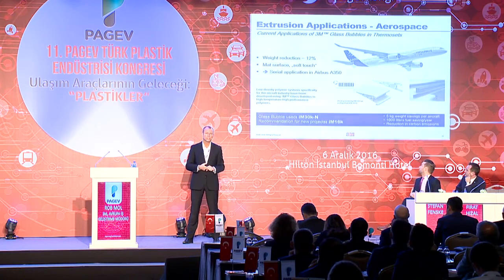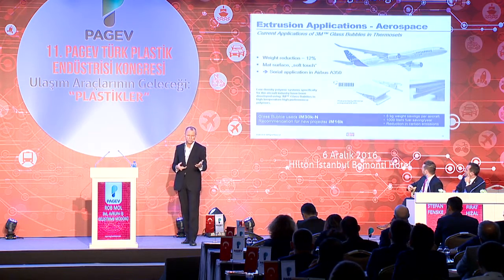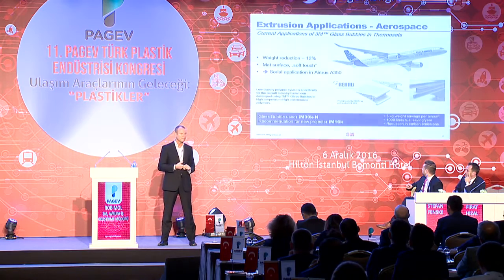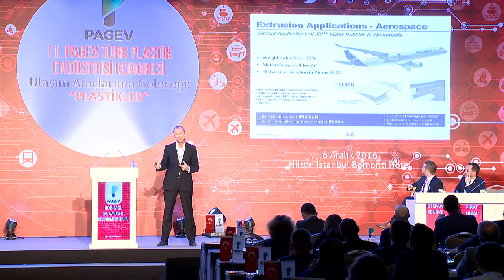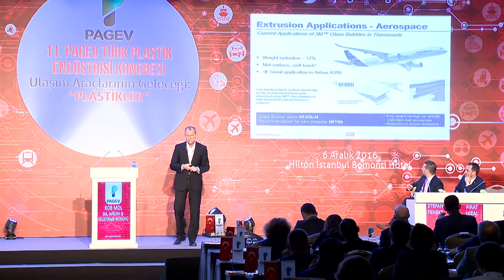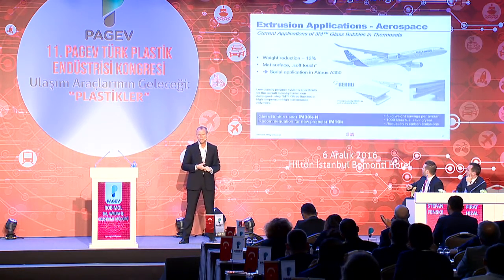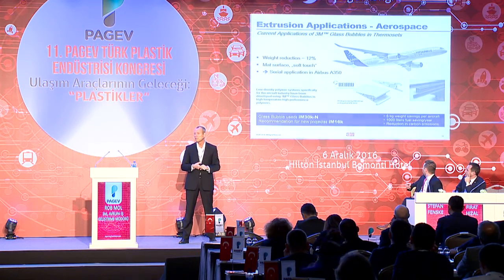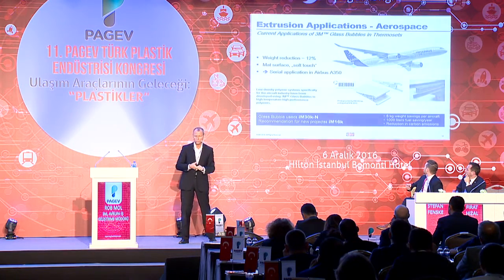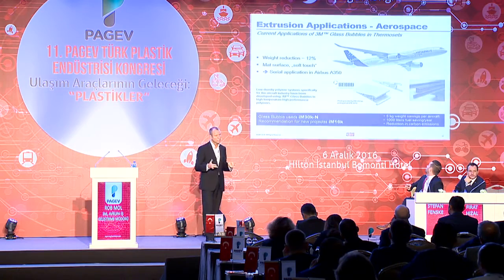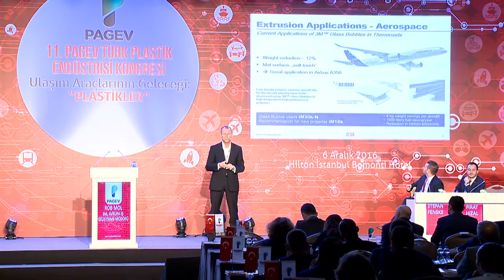You can also use the glass bubbles in thermoset applications, like for instance here with the Airbus A350, where some of the parts of the armrest are filled with glass bubbles. They managed to reduce the weight there by about 12%, which translates into a fuel consumption reduction of about 1,000 liters per year of kerosene for one of the planes.